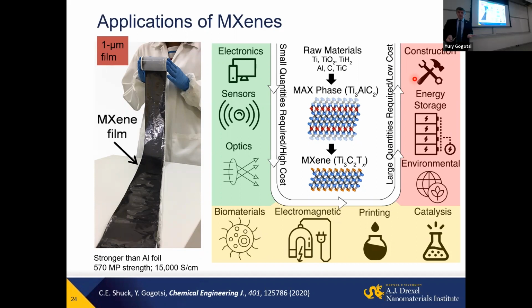And we can really manufacture it here, because you see, this is a 1 meter long, 10 centimeter wide film of MXene. It has just 1 micron thickness and you can handle it. You can lift it, you can handle it separately. It has strength exceeding that of aluminum foil that you use to wrap up your breakfast. And 15,000 Siemens per centimeter. It was made by just taking this colloidal solution of MXene, doctor blading it over the surface and drying. Very simple, very efficient process. And we can use it, for example, as a current collector in a battery with 10 times smaller thickness compared to, say, copper, and it means much lighter.